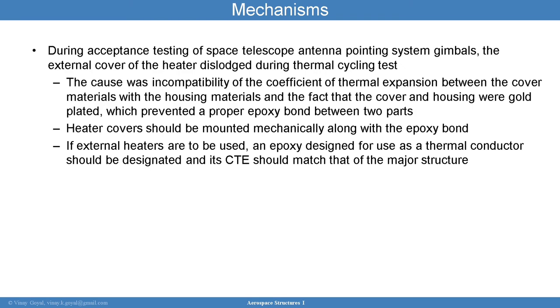During acceptance testing of Space Telescope Antenna Pointing System gimbals, the external cover of the heater dislodged during thermal cycling testing. So the cause was incompatibility of the coefficient of thermal expansion. So you want to pay attention to coefficient of thermal expansion. It's usually not paid attention to, but the CTE mismatch between a metal and, say, a bond, that thermal expansion can cause a failure. And so that caused an issue in this case because of CTE.